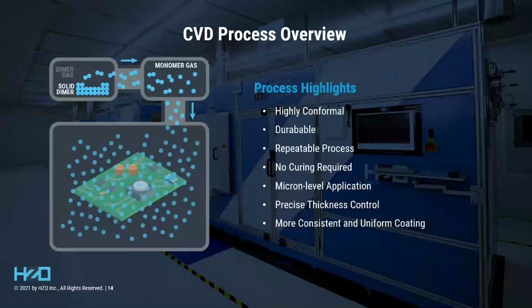In this case, there's no curing and the parts aren't in a furnace. This is in situ polymerization. It's room temperature. And the polymer is fully inert when it comes out of the chamber. So the polymer chains have fully reacted. There's no curing, there's no drying. Everything is protected fully when it comes out of the chamber.